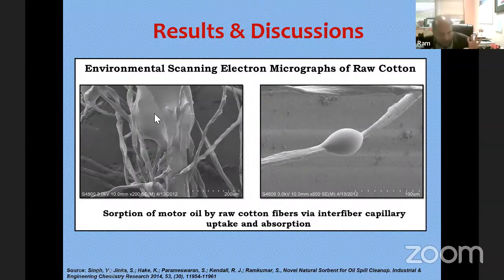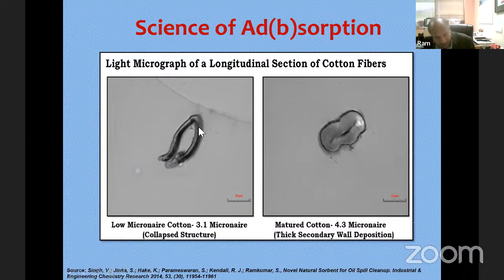You can see beautiful adsorption and spreading, formation of film. By the time it spreads, individual cotton absorbs, and you can see much better blooming, beautiful blooming spherical images. And this is the reason I told you this one thing like a cow's foot is basically the immature cotton. There is no cellulose deposition. When there is no cellulose deposition, the cotton fiber is thinner, so you are able to pack more fibers in a given volume. Whereas on the right-hand side, you can see fine mature cotton with a lot of cellulose deposition. That is very important for dye deposition, for dyeing. Whereas for our application, we need immature cotton where the cellulose deposition is less, so that you can pack more fibers in a given area as against regular fiber.